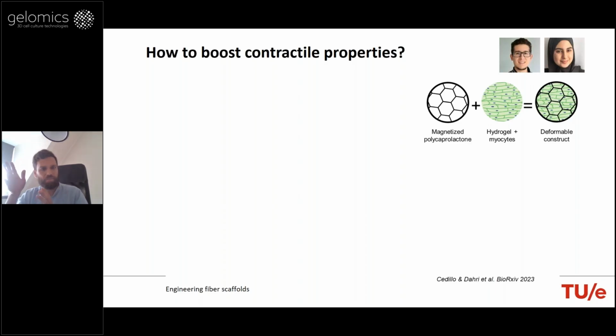On the other angle, we tried to keep the thickness of this construct with the same cell density, but now instead of printing PCL, print a material that can be externally activated. In this case, we looked at magnetized polycaprolactone. And the thinking here was, if we can further boost the contractile properties of this patch, we can eventually replace the contractile force that was lost after infarction.